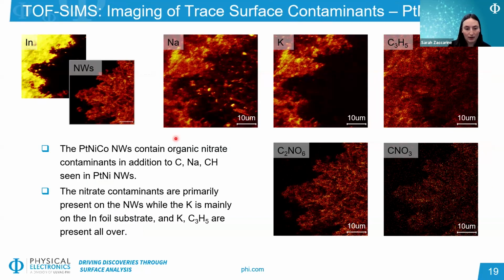So next we're going to look at the nanowires that were a cobalt nanowire coated with bimetallic platinum and nickel ALD deposition, because again, this can change the resulting platinum and nickel chemistry that's present after all these different processing steps. So here we're starting with looking at the surface contaminants again.